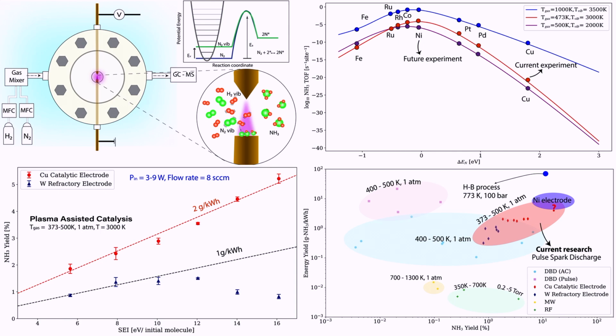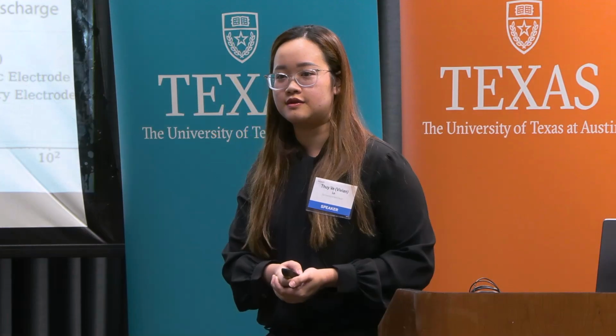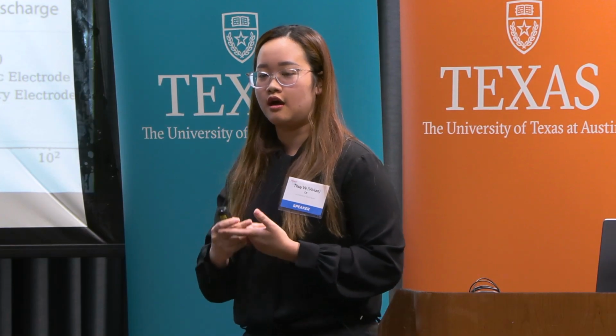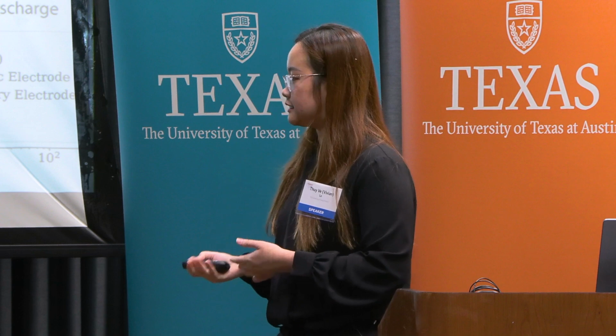So using the pulse spark discharge combined with the copper electrodes, I think we are in the upper range of what we have compared with other plasma-based approaches. And we decided to test the nickel electrode, which showed higher production from these simulations. And so the key question is, what is the acceptable energy cost where we can synthesize ammonia on site?